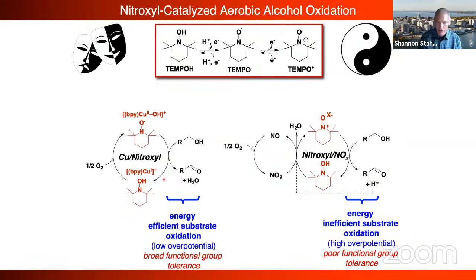And so now we do very efficient aerobic oxidation with a very chemoselective, low driving force catalyst using copper TEMPO compared to oxoammonium. Oxoammonium is still a great catalyst, and so many substrates are fine with TEMPO. But what this means is that if you want functional group compatibility, you're probably going to want copper TEMPO because your functional groups, heterocycles, and other things are going to tolerate that at the expense of O2 reduction efficiency. But who cares? We're synthetic chemists. What we care about is the organic molecule, right? If we're driving a fuel cell, we really care about this, and we want to maximize the efficiency of O2 reduction. But if you're a synthetic chemist, you may not want to.